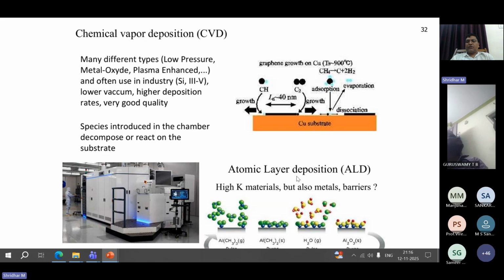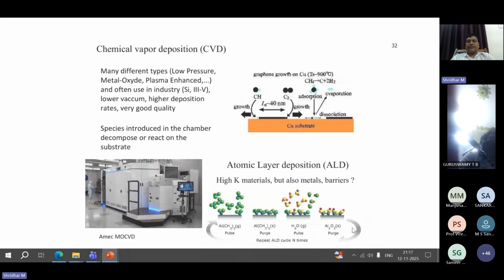Atomic layer deposition, you can see high-K materials and also metal barriers. You can see here these materials evaporate and come and sit here, and another material will come and sit and form Al2O3. On the substrate, Al2O3 is sitting on this material. Atomic layer deposition it is.